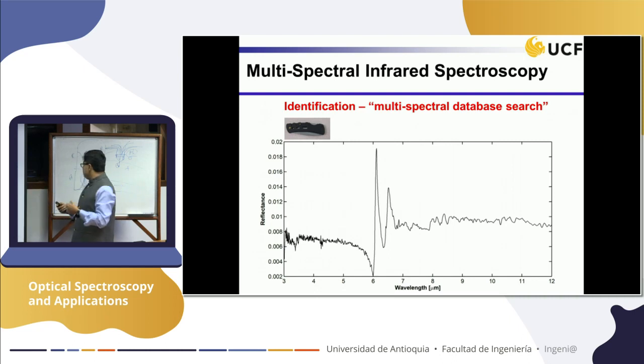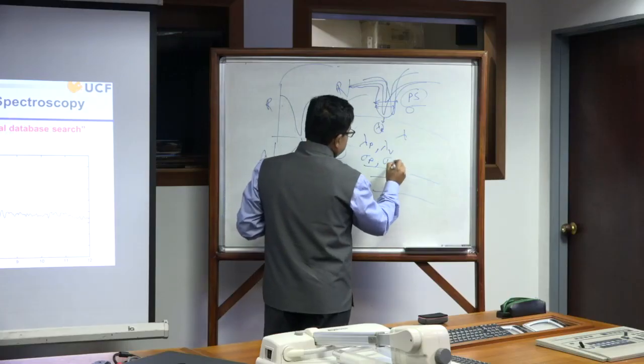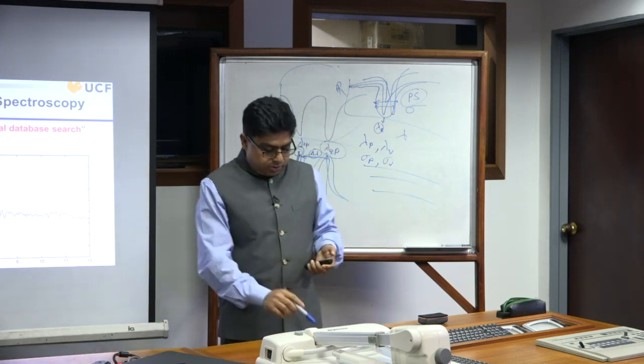In this case, what is a fingerprint? A fingerprint is the peak locations and the valley locations and their distribution, the change of width. Based on the additives, the company that manufactured the plastic, the heat treatment, and the rolling process, you can change the resonance based on the compactness. Light is very sensitive to material compactness and density change. So you not only measure lambda peak and lambda valley, but also their corresponding distribution variation. That's what you capture.